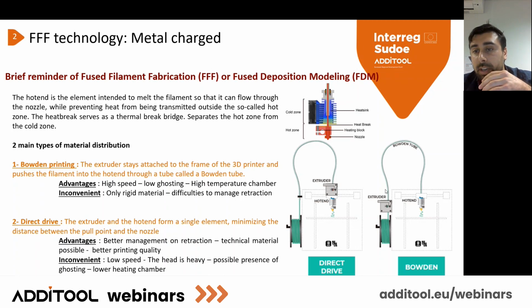However, the inconvenient, we can push only rigid materials because we will have difficulties to push the filament. If it's soft, for example, we will have some distortion on it. It's not well guided, and it's more difficult for fragile filament or very soft materials. And also, it's difficult to manage some retraction on the filament because we have a lot of length on it.